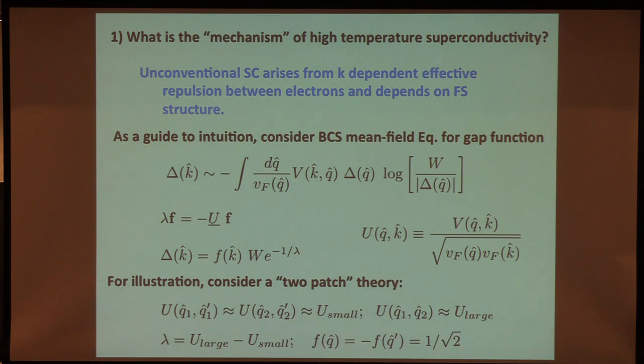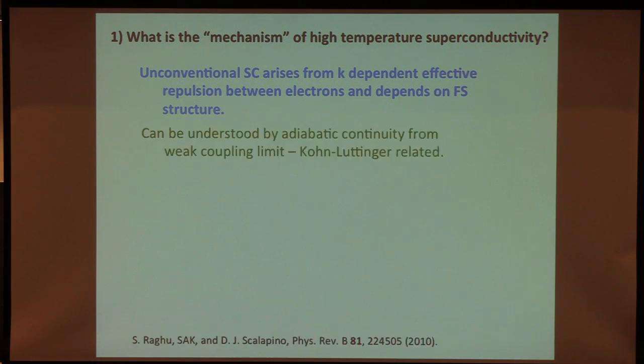And now, we all know how to diagonalize 2 by 2 matrices. And so in particular, even if U is positive, so that is to say, even if I have only repulsive interactions, so long as U large is bigger than U small, then this effective interaction is attractive. Lambda will be positive, but the other consequence is that the eigenvector is a sign-changing eigenvector that's plus on one piece of the Fermi surface and minus on the other. So we get unconventional superconductivity when the repulsive interaction at large momentum transfer is larger than the repulsive interaction at small momentum transfer, and an inevitable consequence of that is that we have a superconducting gap that changes signs on different parts of the Fermi surface.